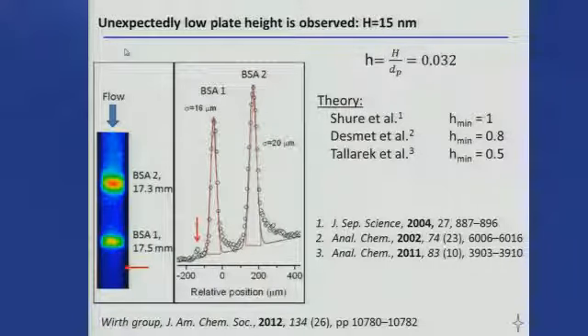But we started making some measurements using pressure-driven flow, since we had this nice flow. And this is, in the chromatography world, a very shocking sort of thing. So this is bovine serum albumin, which usually gives really broad peaks, emerging near the end of a 2-centimeter long capillary. One's labeled much more than the other, so that changes the retention time. So we have 2 different peaks coming out, and they're cleanly resolved. And this is a capillary 75 microns wide, which means that the zone widths are microscopic. And so you don't usually use a microscope for your chromatographic detector. And so pressure-driven flow, extremely narrow peaks.